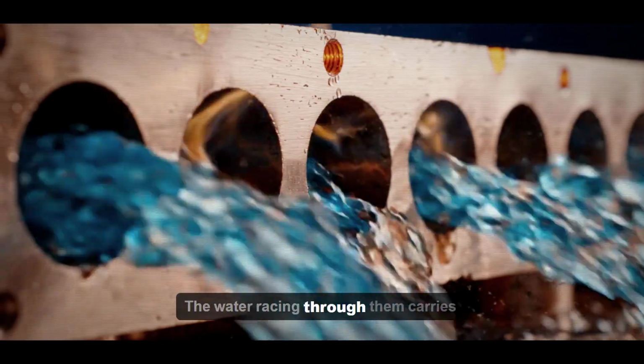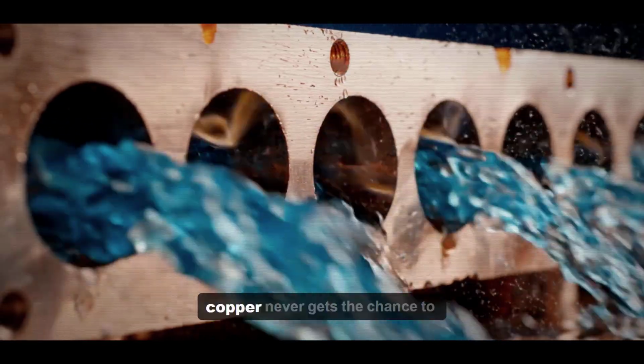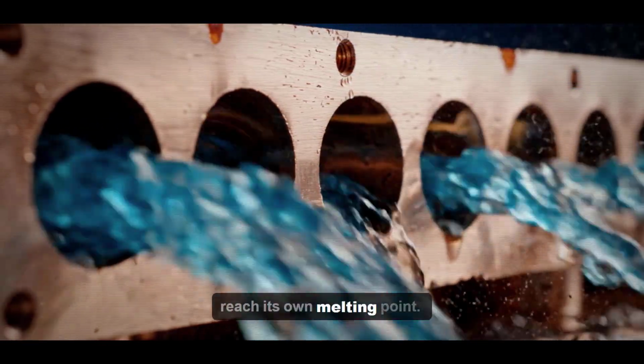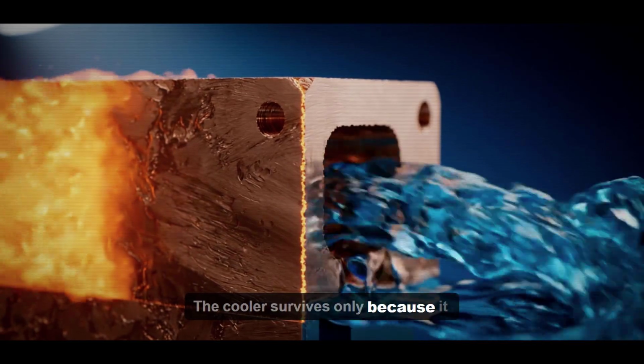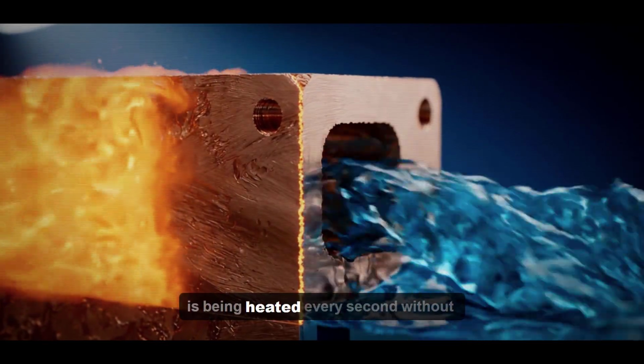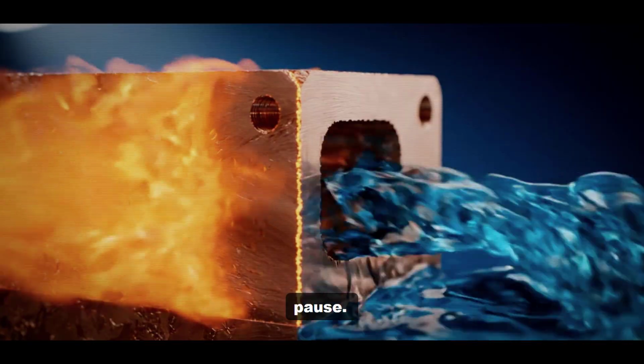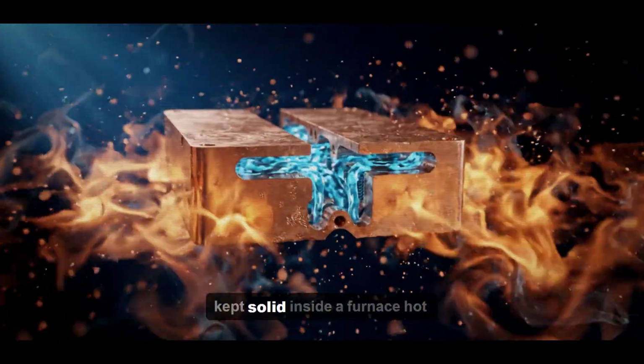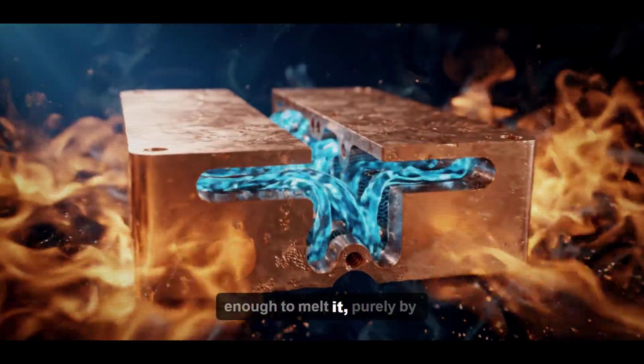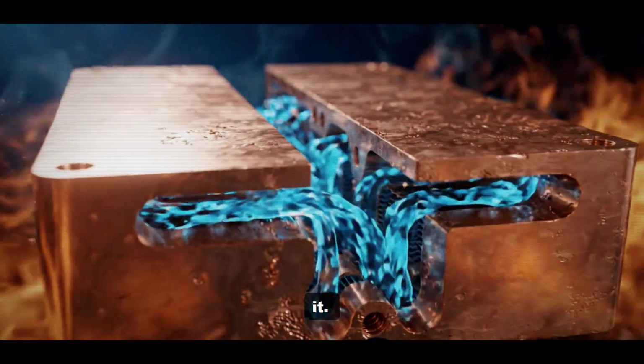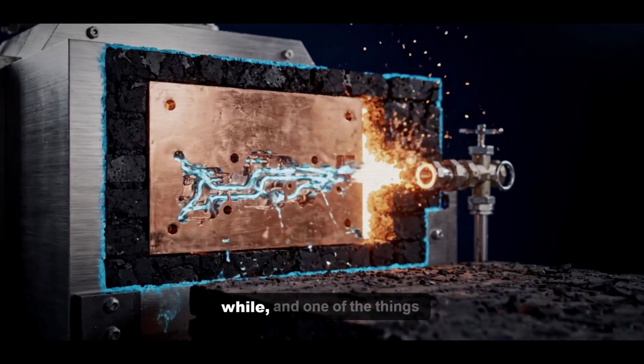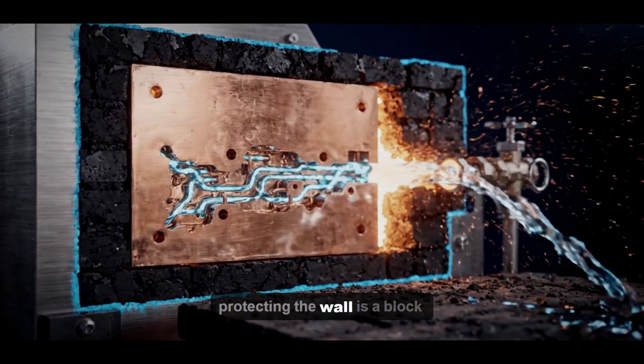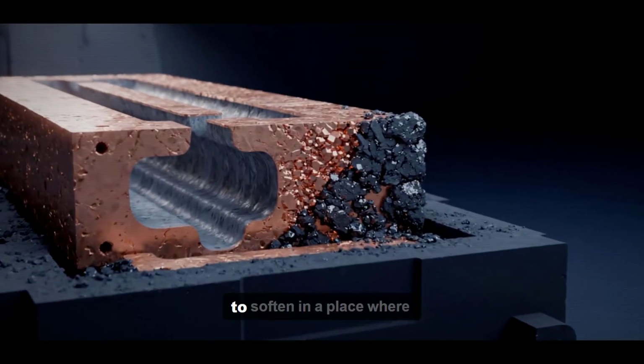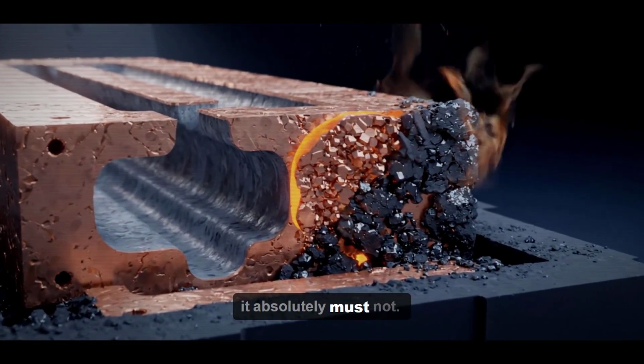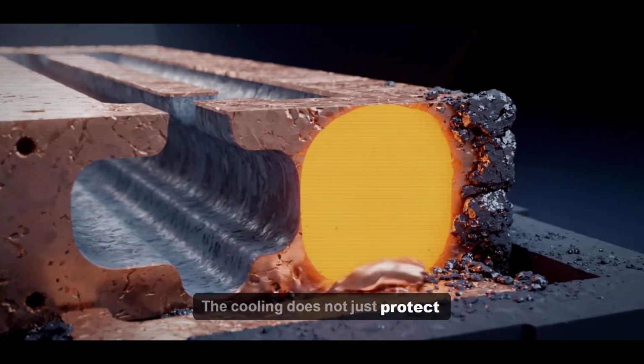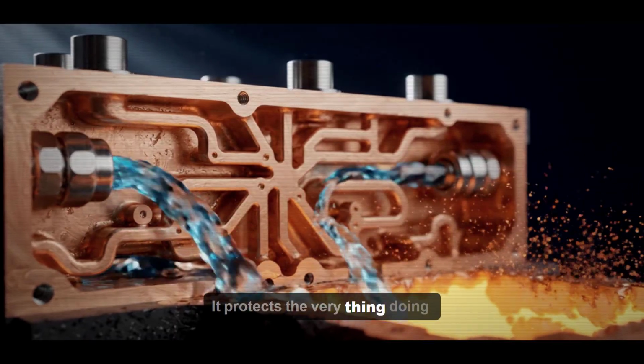The water racing through them carries heat away so fast that the copper never gets the chance to reach its own melting point. The cooler survives only because it is being cooled harder than it is being heated every second without pause. It is a piece of copper kept solid inside a furnace hot enough to melt it, purely by the speed of the water inside it. Stop that water, even for a while, and one of the things protecting the wall is a block of copper that will now start to soften in a place where it absolutely must not. The cooling does not just protect the brick, it protects the very thing doing the cooling.